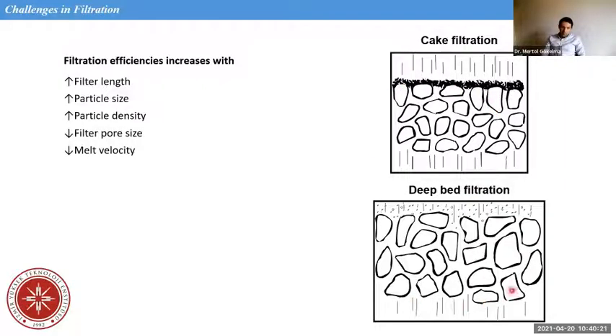Most of the time, we have a combined behavior of particles, and the filtration efficiency increases with increasing filter length or height. And efficiency increases with increasing particle size, easier to filter. So the small particles are a challenge here, and efficiency also increases with increasing particle density. And filtration efficiency increases with decreasing filter pore size. Smaller size of pores filter better, and the efficiency is high, but not for a long time, because then you have incredibly high cake formation and clogging.